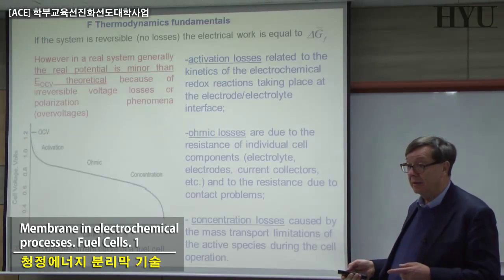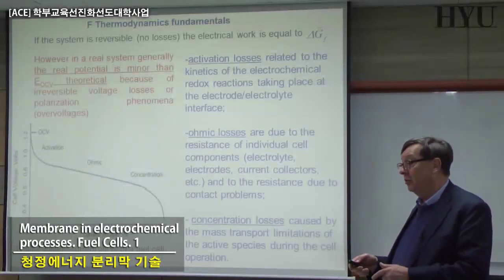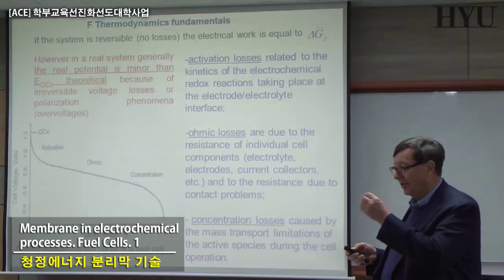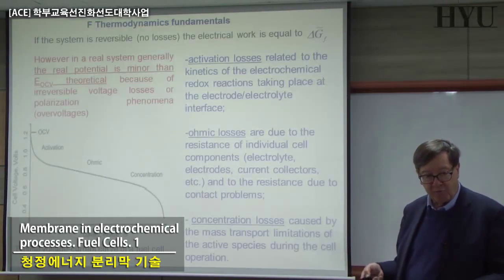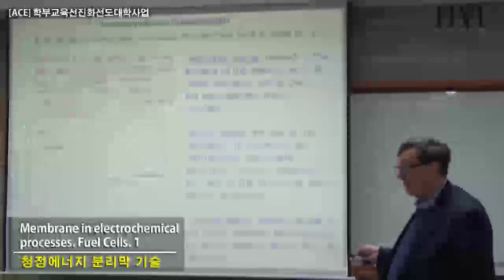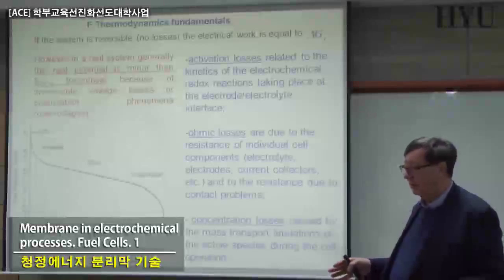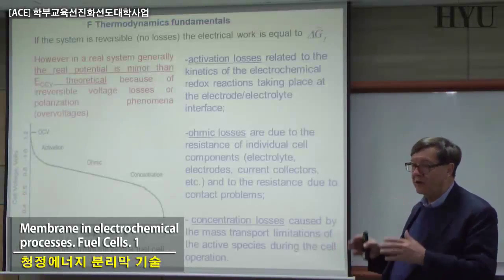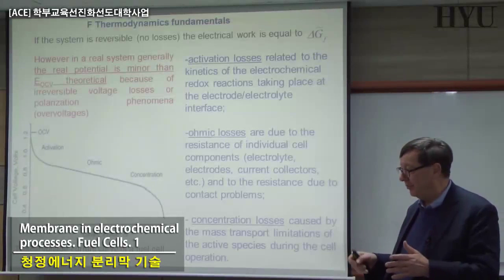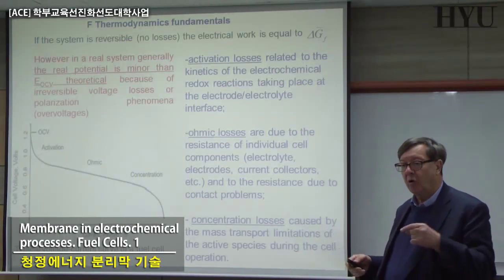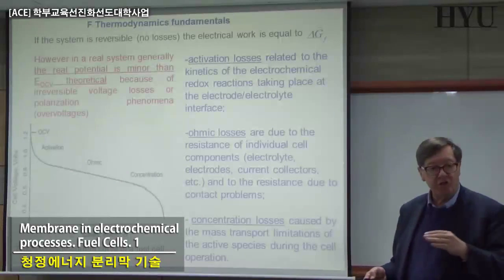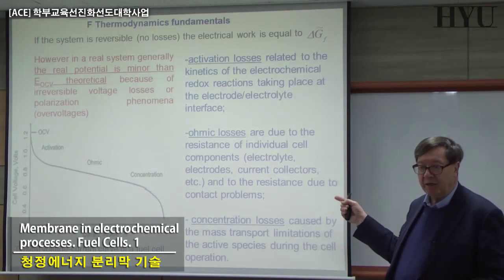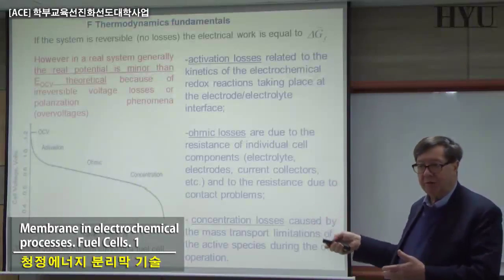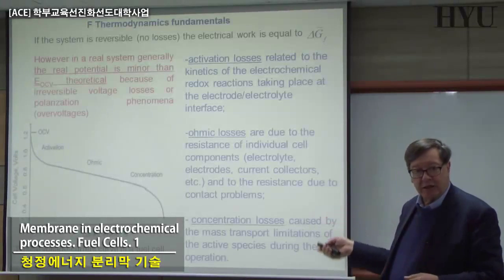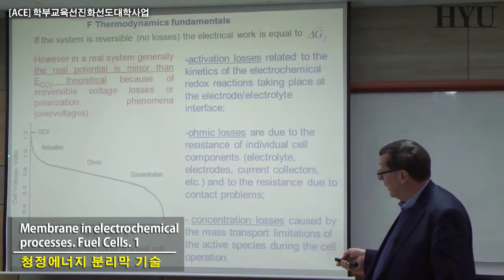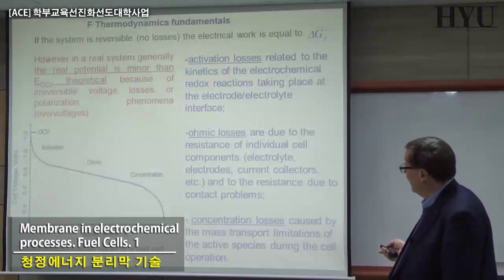And the difference is related, as you learned already very well, in this case also to the membranes, the intrinsic property of your membranes. But in principle, most of the phenomena that make a difference between the theoretical voltage and the real one have nothing to do with the membrane itself, but with the interfacial phenomena, or the phenomena which take place in the system that we call concentration polarization, thermal polarization, overpotentials of different kind. These are the ones that don't give you the number that you can obtain just making a simple calculation with the delta G and delta H of the transformation that is taking place in the system, hydrogen plus oxygen, etc. And as you can see here, the difference is not small.